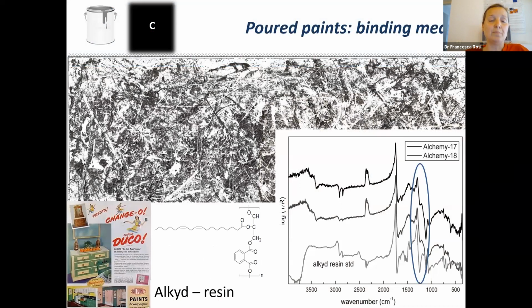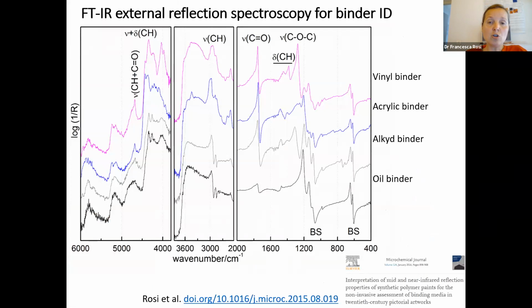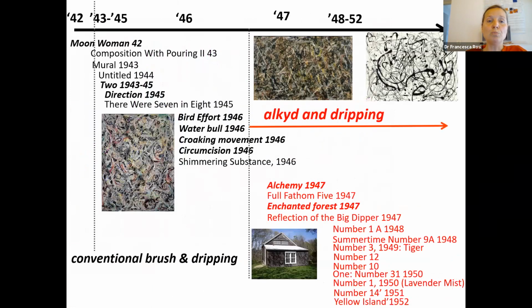And in fact, we detected the presence of the alkyd medium in his masterpiece Alchemy for dripping the black painted area. There was present both opaque as well as brilliant and shiny black. All of them are painted in a dripping way with the alkyd. Through FTIR spectroscopy, we can differentiate different modern binders as well as more traditional binders. So exploiting this specificity, we were able to make a sort of temporal map of the use of the alkyd painting within the painting of Pollock, correlating the compositional information with the visual appearance and information regarding the painting technique.